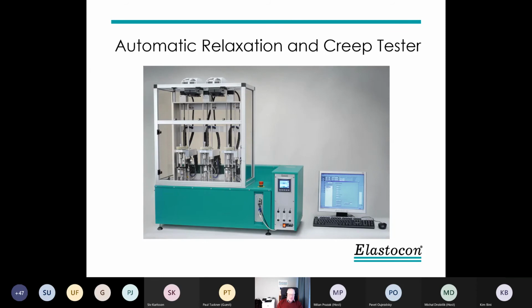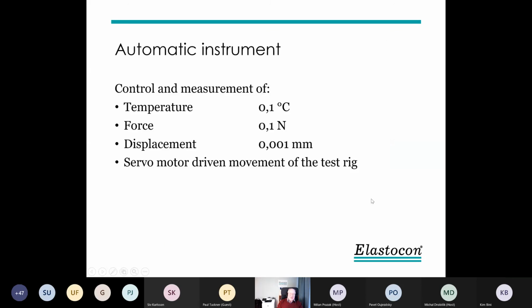Another instrument we developed quite a lot of years ago is an even more automatic relaxation and creep tester. It can also test creep, because here we have 3 test rigs. They are motorized for going up and down, and we have a servo motor doing the compression of the sample. And then we can have a temperature up to 300 Celsius inside here. The important thing here is if we want to measure creep especially, which we can do because we can set it on a force level and keep that force level and measure the creep. We have an accuracy of 1/1,000 millimeter and a resolution of 1/10,000.